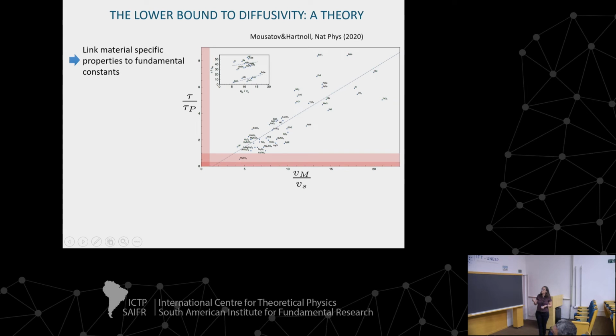So after this work, there was a theory work from the group of Hartnoll, and basically their idea was to consider the melting temperature as the highest energy scale that the crystal can have. Because above this temperature the crystal will melt, and therefore the crystal doesn't exist anymore, so it's the top energy scale that we can consider. It's quite a simple model: a harmonic oscillator with just one anharmonic term. They joined this with the Heisenberg uncertainty principle, considering the energy associated to the melting energy. So they defined what is called the melting velocity, and they showed that the sound velocity is bound by this melting velocity.